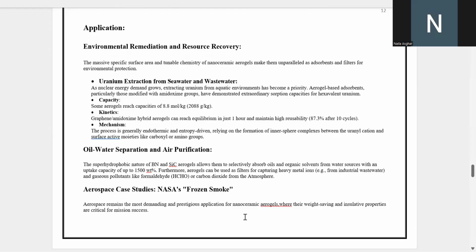And the second application is oil-water separation and air purification. The superhydrophobic nature of boron nitride and silicon carbide aerogels allows them to selectively absorb oil and organic solvents from water sources with an uptake capacity of up to 1500%. Furthermore, aerogels can be used as filters for capturing heavy metal ions, for example from industrial wastewater, and gaseous pollutants like formaldehyde and carbon dioxide from the atmosphere.